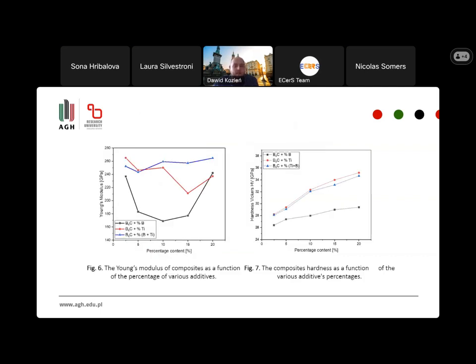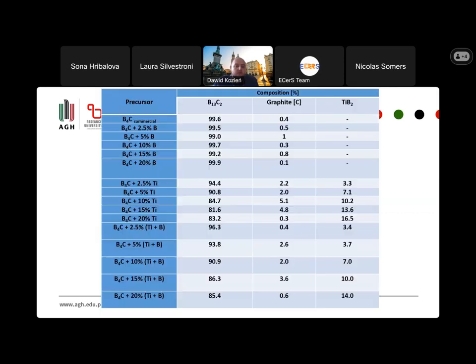The results obtained by our research group can be compared to boron carbide with titanium and silicon carbide, and the same with the hardness and other things. So it's quite good because we didn't assume this. Maybe some interesting information is that with the boron additive, the boron takes the residual graphite that is obtained during the sintering. So the boron can take the carbon into the structure, and we don't have free carbon in the composite that weakens the structure of the composite.